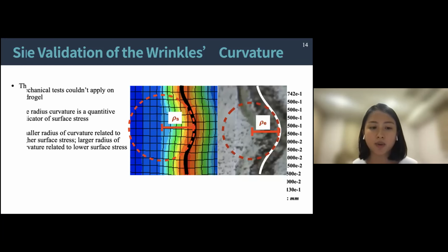So because the hydrogel is very soft and fragile, it is hard to apply the mechanical test on it. So we use the radius of curvature as a quantitative indicator of the surface stress. So the smaller radius of the curvature was related to the higher surface stress, and oppositely, the larger radius of the curvature was related to the lower surface stress. And of course, the initial size of both is identical. So it is acceptable to compare two of them.